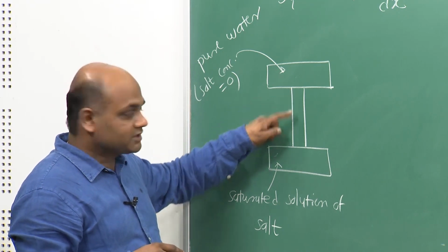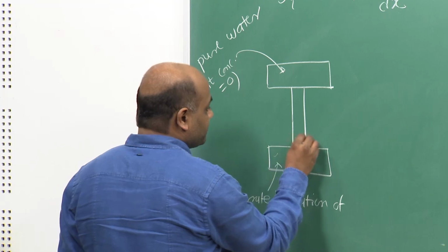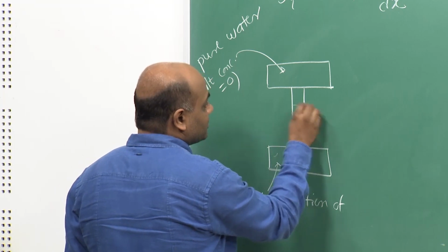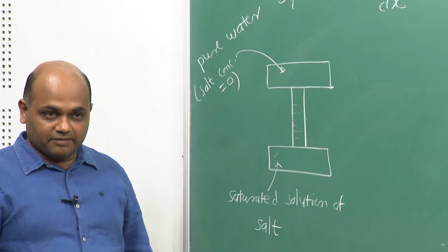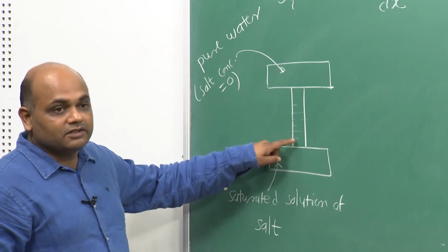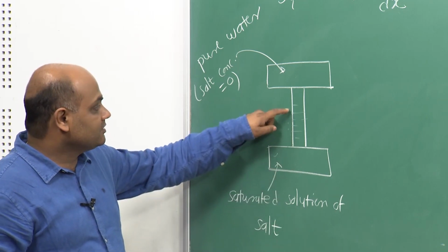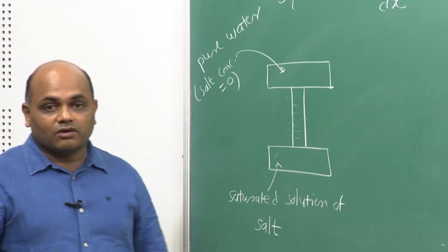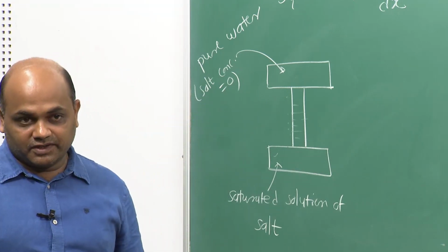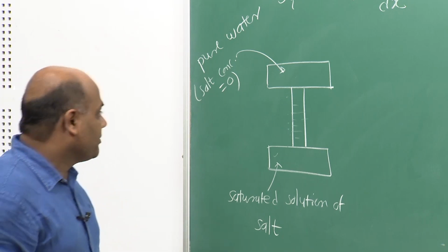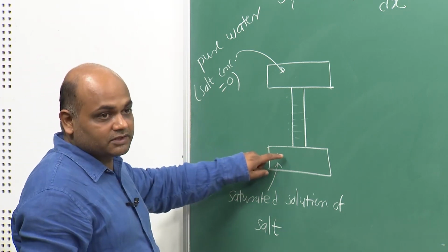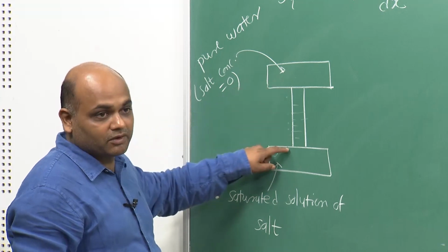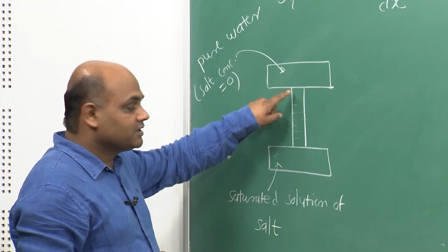In non steady state, the concentration at any x position, the horizontal position, will change with time, but in steady state the concentration at any x position, that is along the horizontal plane, will remain constant, it will not change with time, that is the steady state. So, by making sure that the concentrations at the two terminals remain constant, we can develop a steady state.